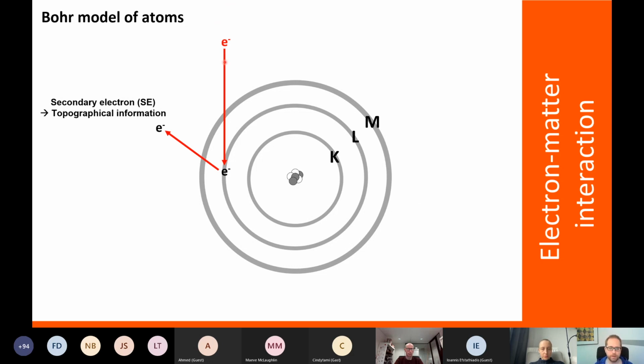One thing that can happen is that an incoming electron here in red hits an electron on one of the shells and kicks it out from the shell. This we call a secondary electron, which will give us topographical information, as I mentioned earlier, one of the basic pieces of information we can get within a scanning electron microscope. But also, when an electron relaxes from a higher shell onto this shell, we can get X-rays emitted, and there will be a dedicated lecture, as I said, on using X-rays for chemical analysis later today.